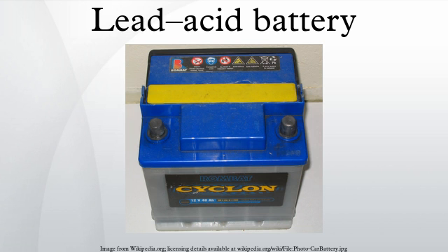Consider a battery that has been completely discharged. If it then is given a fast charge for only a few minutes, the battery plates charge only near the interface between the plates and the electrolyte. In this case the battery voltage might rise to a value near that of the charger voltage. This causes the charging current to decrease significantly. After a few hours this interface charge will spread to the volume of the electrode and electrolyte. This leads to an interface charge so low that it may be insufficient to start the car. As long as the charging voltage stays below the gassing voltage, battery damage is unlikely, and in time the battery should return to a nominally charged state.